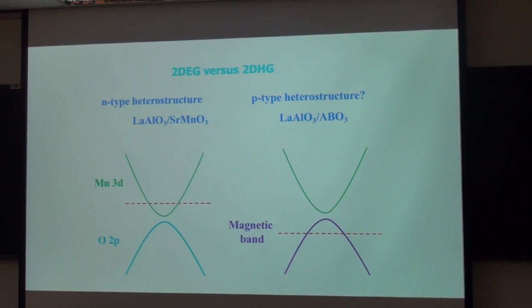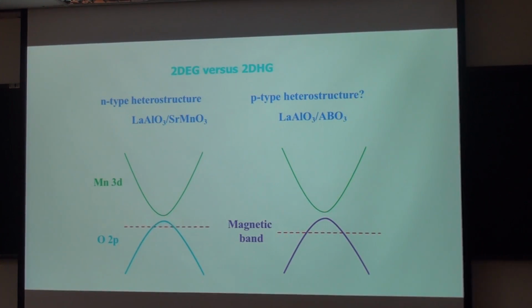After this work, we have realized a spin polarized two-dimensional electron gas in this heterostructure. We ask ourselves, is there a spin polarized two-dimensional hole gas? But unfortunately, for this system, the valence band is composed mainly of the oxygen 2p state. As I mentioned above, the holes located at the oxygens will not be stable. They will be compensated by the existence of oxygen vacancies. So we should change our strategy.